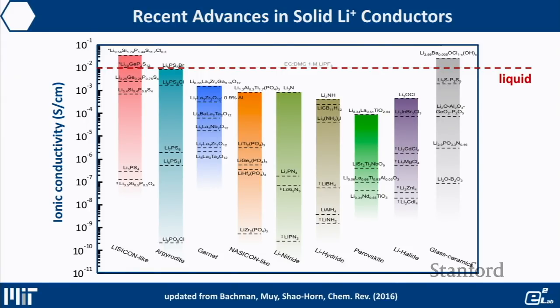So the challenge today is that none of these electrolytes are stable against the positive electrodes we use today, nor the negative electrode we use today in lithium-ion batteries, right? So we essentially need to search for more electrolytes that are not only conductive, but also equally stable against the positive and negative electrode to enable stable solid-state lithium-ion batteries. Right? And as you can see, within each family, the ion conductivity can vary by many orders of magnitude. Some are over 10 orders of magnitude.